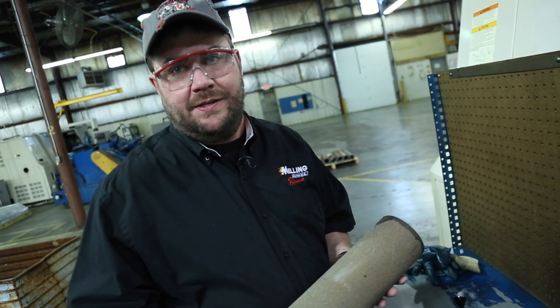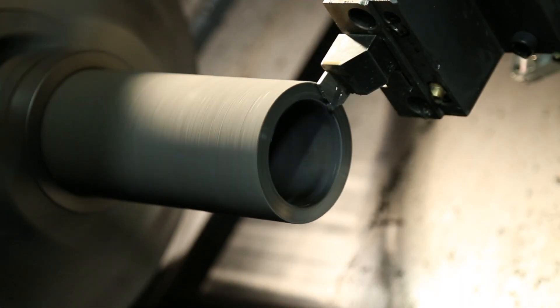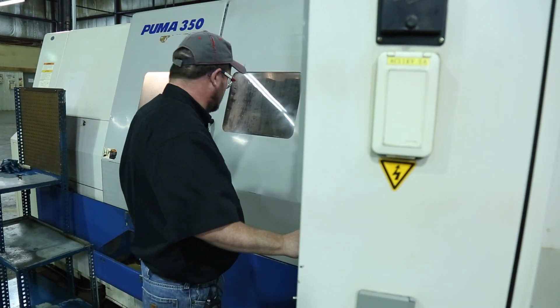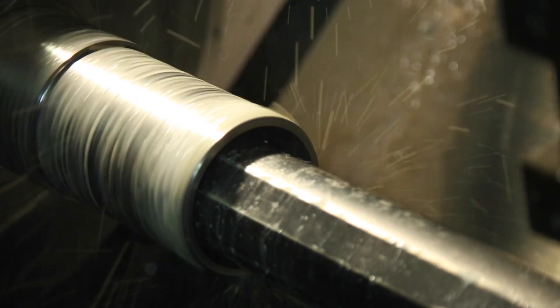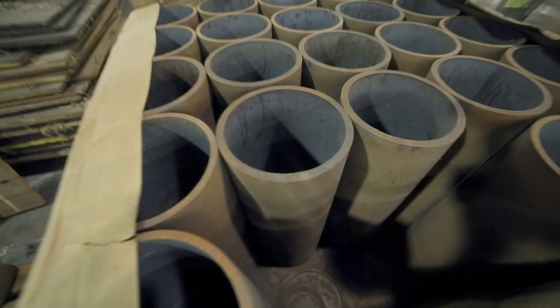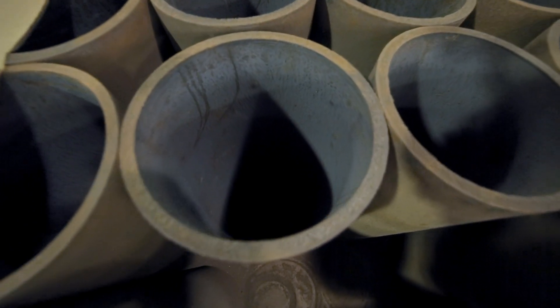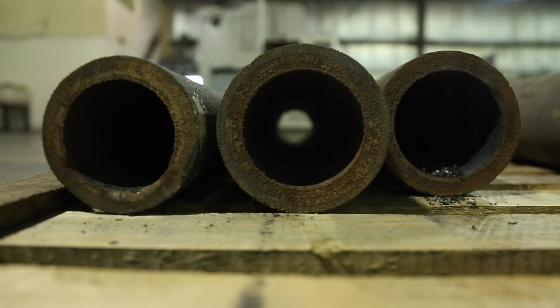This is a casting we use to make custom sleeves. We specialize in manufacturing centrifugally casted iron cylinder liners to small tolerances as small as plus or minus a half a thou. This is a custom sleeve for a 1932 Rolls-Royce. The material used in Melling Cylinder Sleeve Liners has a Brinell Hardness of 212 to 293 and a 30,000 PSI tensile strength.